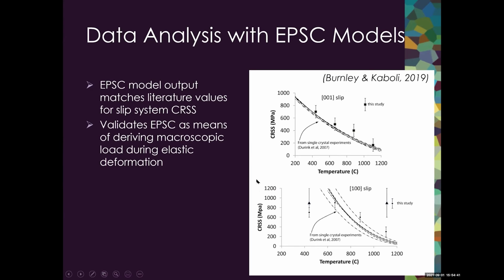So these figures to the right show the critically resolved shear stress as a function of temperature for 001 slip on the upper figure and 100 slip in the lower figure. The 4 data points on the graphs are the critically resolved shear stresses that were obtained from the 4 deformation experiments I showed on the previous slide. And these are overlaying the curves from single crystal experiments by Durinck et al.